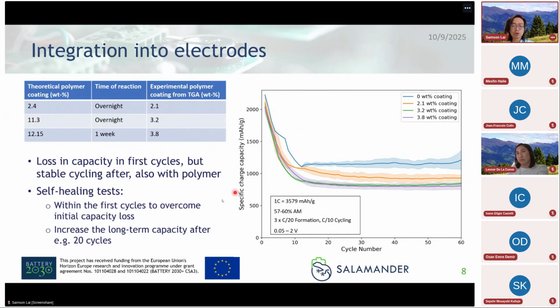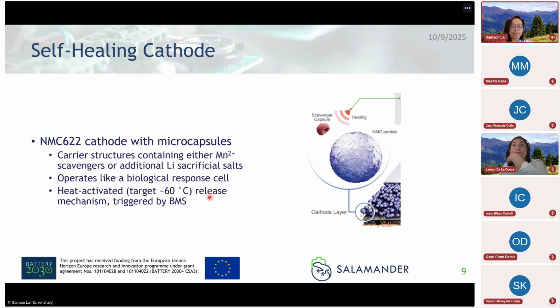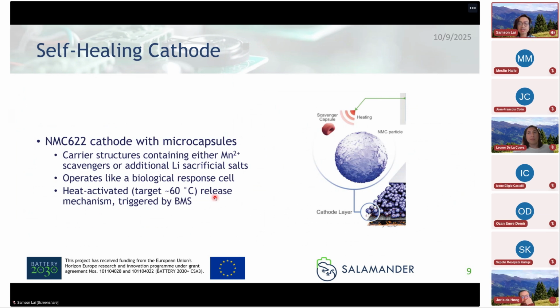On the cathode side, we set this approach with using microcapsules in this platform, carrying these structures. So they either have, for example, manganese scavengers to pick up dissolved manganese ions in the solution, or lithium sacrificial salts. So those can just be activated and sort of increase your lithium inventory. This operates basically a very bio-inspired design from like immune systems or healing, like platelets, and they kind of just float around, and then you can activate them accordingly to release the trigger or the key species inside. So it's relatively straightforward wet chemistry method.